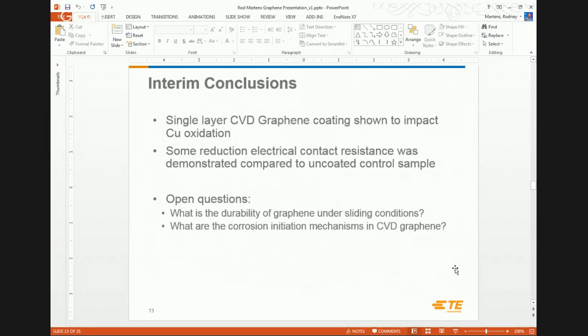But then really the open questions are, I know this is the strongest material ever measured, but if you recall earlier, they were testing in terms of nanonewtons, and our products use loads certainly in the order of newtons. So we're many orders of magnitude off there. And then also, what are the fundamental corrosion initiation mechanisms in CVD graphene? Because at a certain point, I believe that we can actually corrode through it. So let's look a little deeper there.